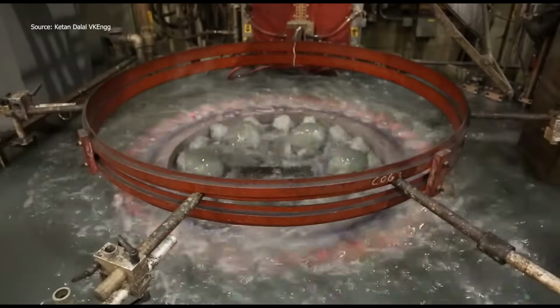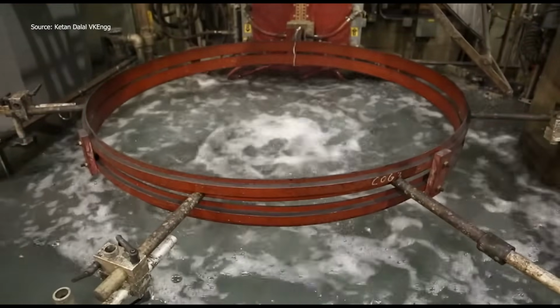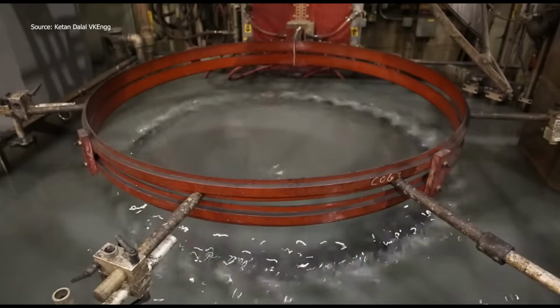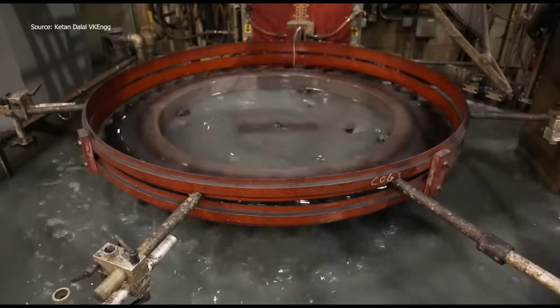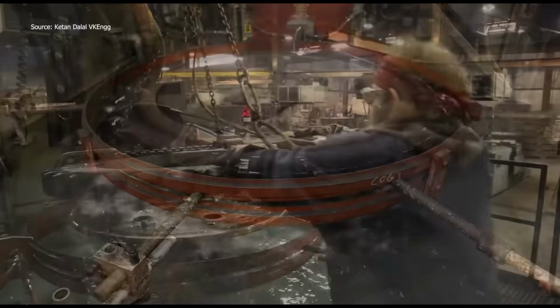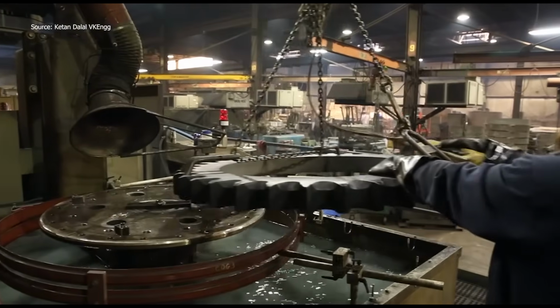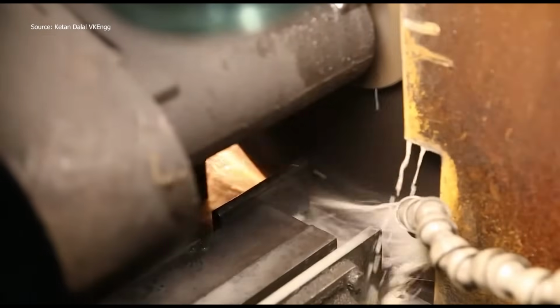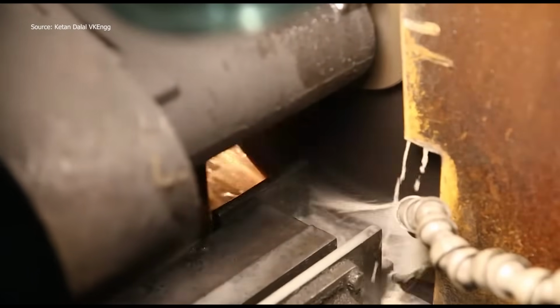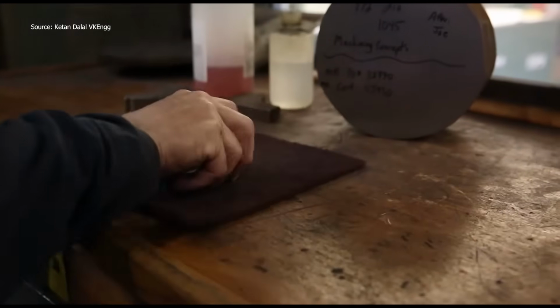In seconds, it reaches transformation temperature, then quenches instantly with a controlled spray. Surface hardness rises dramatically while the core stays tough and ductile. Every setting, spin rate, coil position, temperature, is programmed and recorded, ensuring consistency across all parts. Operators even test cross-sections to verify hardness, depth, and pattern.